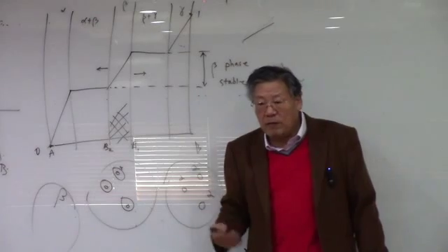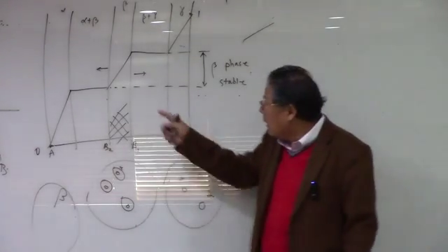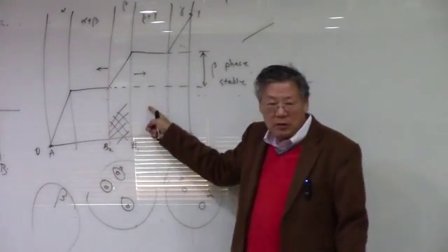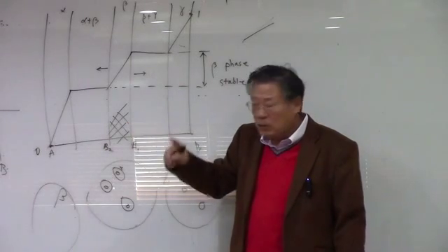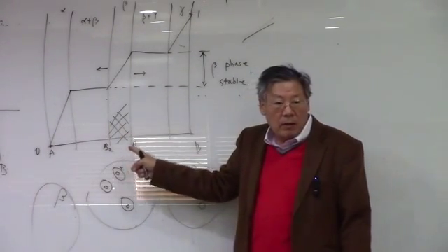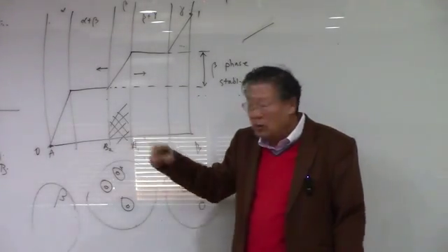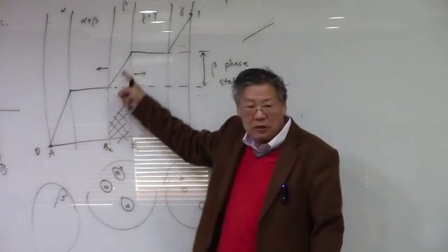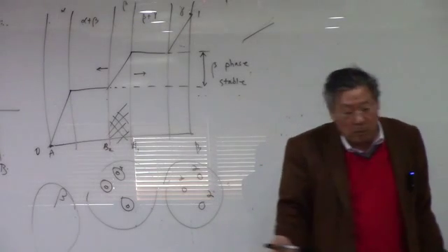So if you want to have a stable battery of 3 volts, then your material has to be in this region or in this region, these plateau regions. If your material is in a single phase region somehow, then by changing the amount of B or A in your material, the voltage is going to change following this curve. So your material is not at 3 volts anymore, okay?